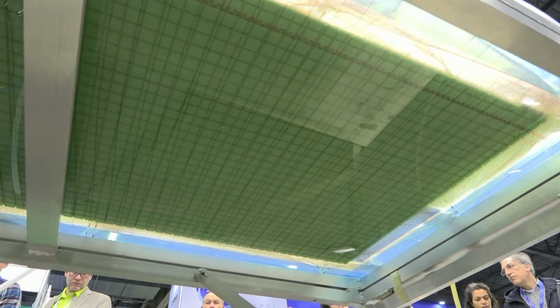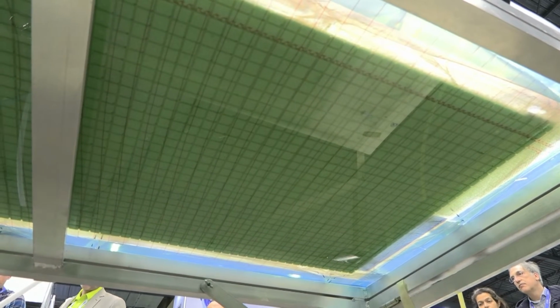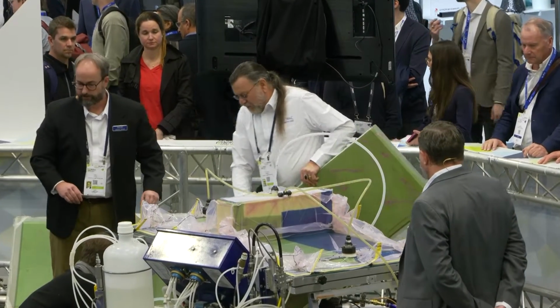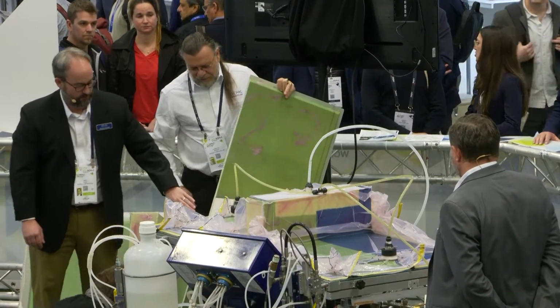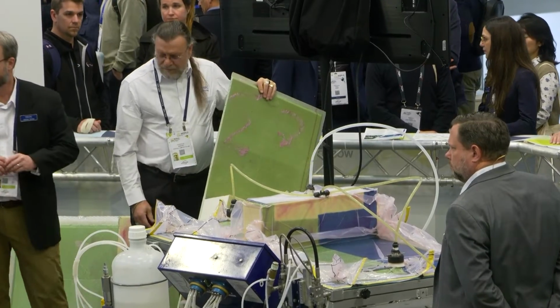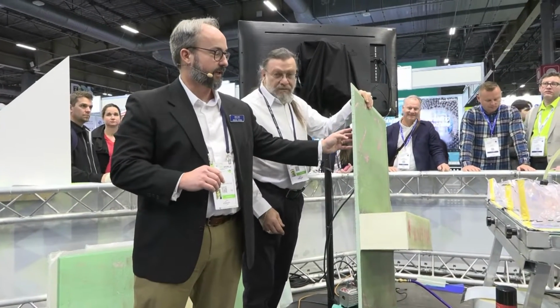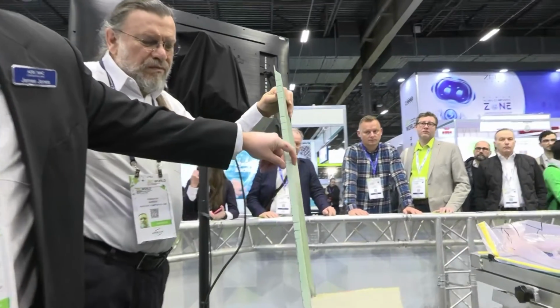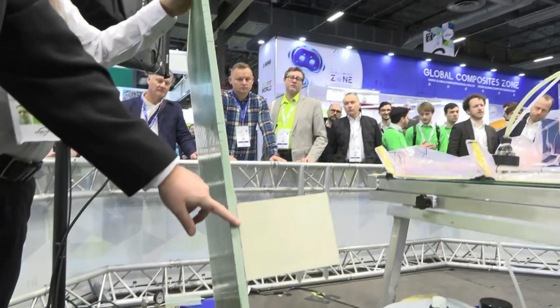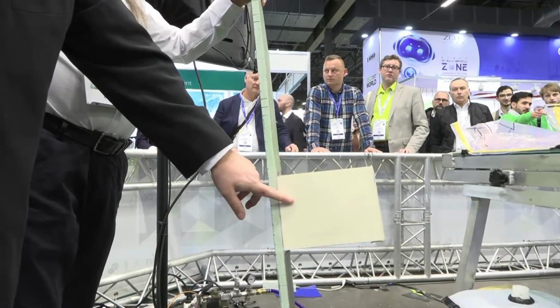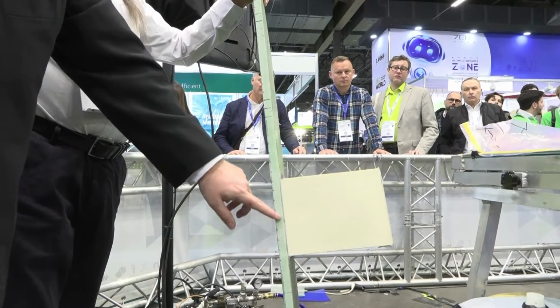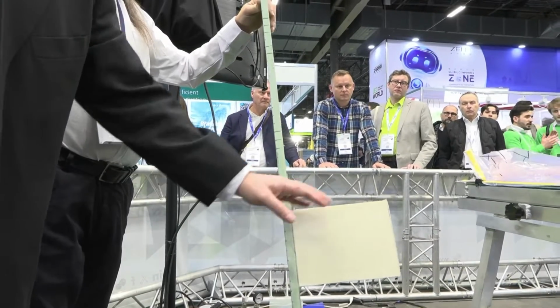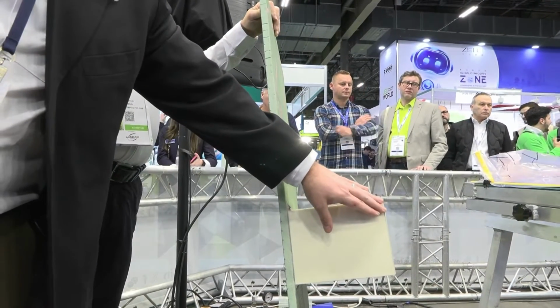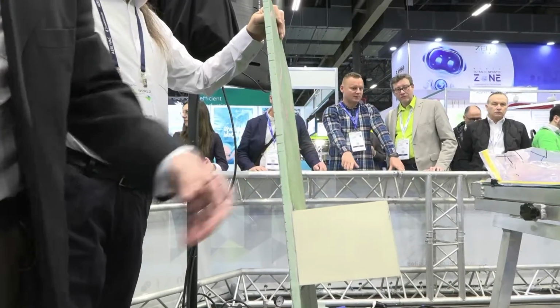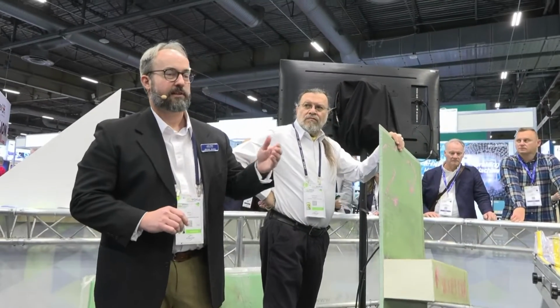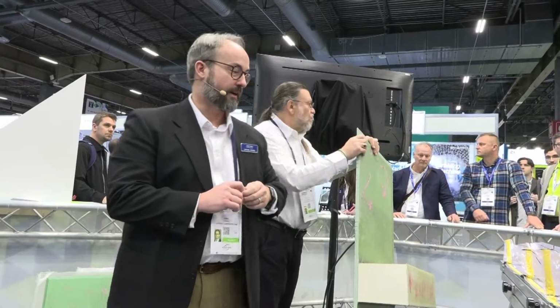Let's grab this. This is the part we made yesterday. If we can get a shot of this. You can see we have very, very thin skins. We just have a 1150 GSM quadraxial on both sides of the core material. And then we've added some material as a pad layer underneath the stiffener. But you can see everything is completely saturated under the stiffener, against the mold surface, and on the stiffener itself. We've actually added additional glass on the cap of the stiffener to give it more strength. But everything is completely saturated, and we don't have any resin being drawn out of the laminate.